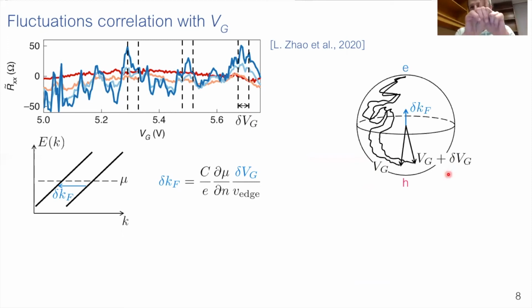So we want to compare the evolution of two spins on a sphere. These two spins feel the same stochastic effective magnetic field due to the Andreev processes. However, due to the difference in the Fermi momentum, there is also a constant component of the magnetic field in the z direction that is different for the two spins. So these two spins at two different gate voltages feel the same stochastic signal and they fluctuate in it, but also because of this constant component, the two spins diverge. So as we pass across the proximitized segment, the conductances are different in the two cases. And that is why the signal changes with the change of the gate voltage.